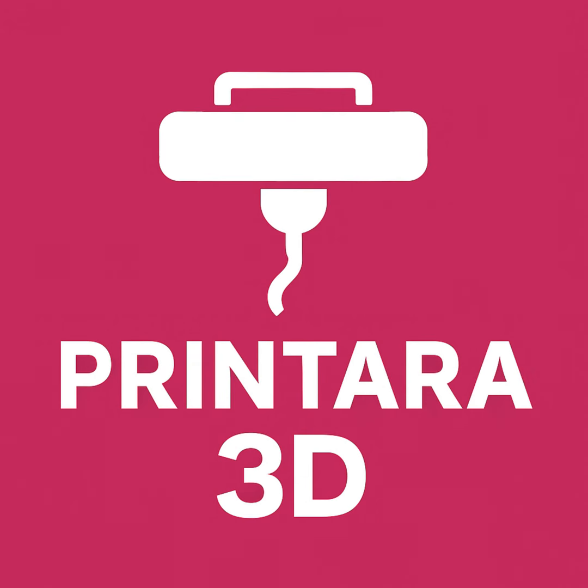Exactly. Let's summarize the journey here. Moving away from standard PLA to engineering materials like PETG, ABS, ASA, or nylon is not just a simple temperature bump. The thermal properties and fluid dynamics are fundamentally different. And your very first line of defense is always attacking moisture. You have to dry the filament for at least 6 hours at the manufacturer spec. Do not rely on the factory vacuum seal. And do not waste your time tuning slicer settings until you are absolutely certain you aren't fighting microscopic steam explosions in the hot end.